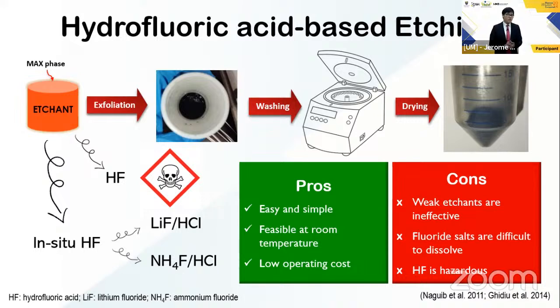And some of the salts have difficulty dissolving in aqueous dispersion, the most prominent being lithium fluoride, exacerbating the already poor etching efficiency. And ultimately, hydrofluoric acid is the main etchant in this reaction. So it's not ideal if you want a totally and completely green MXene.